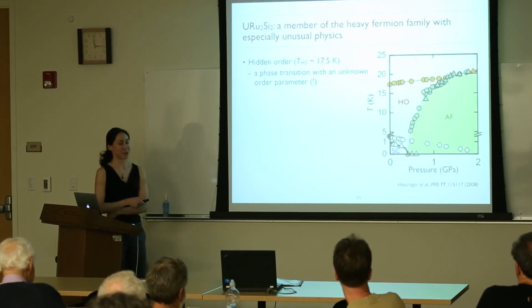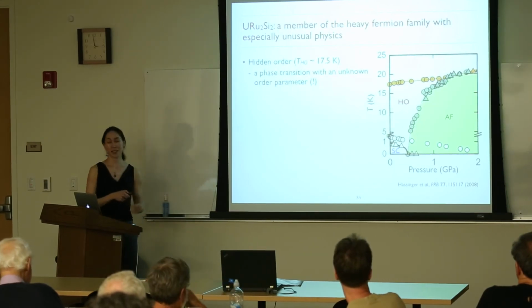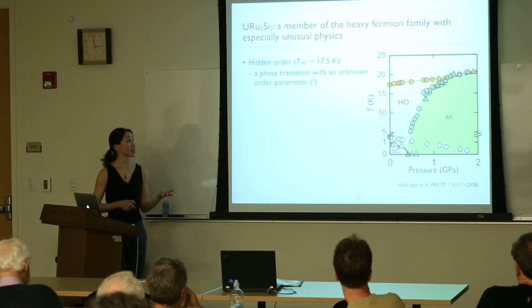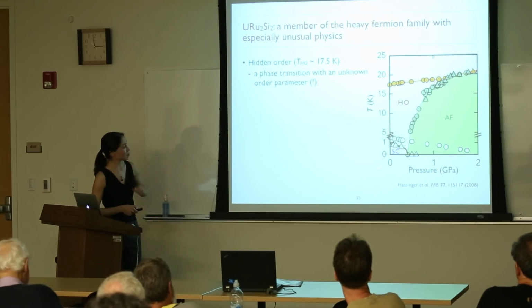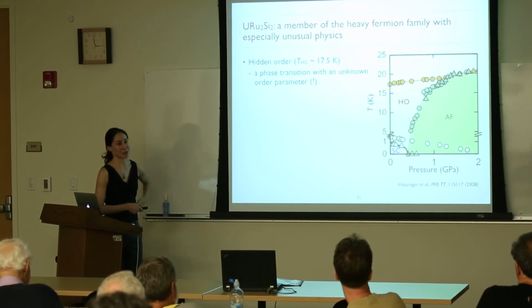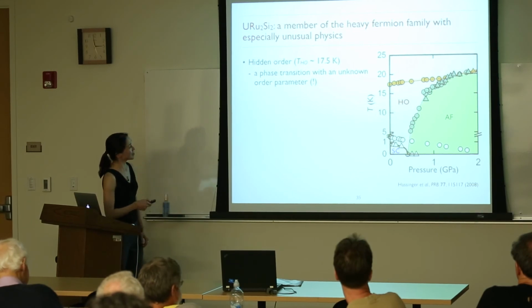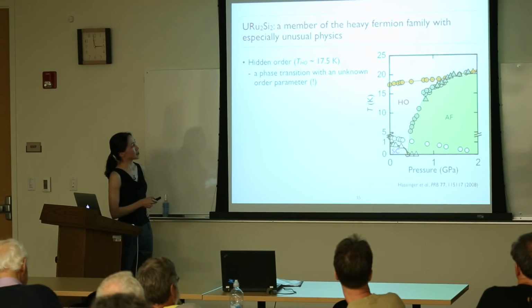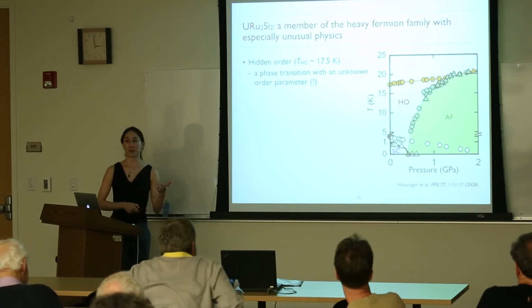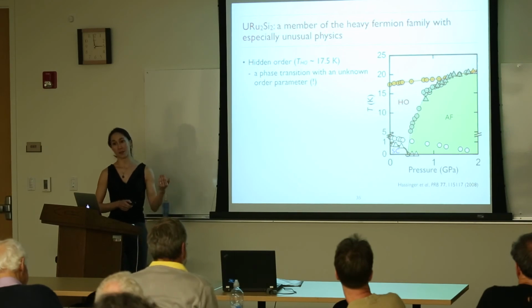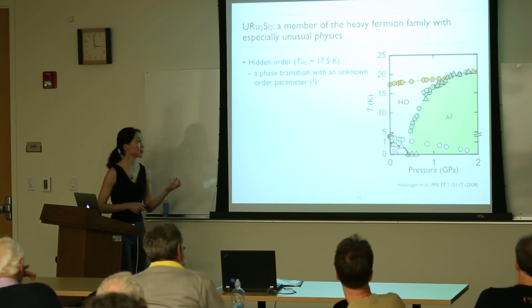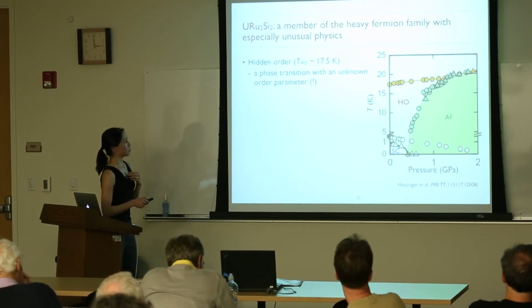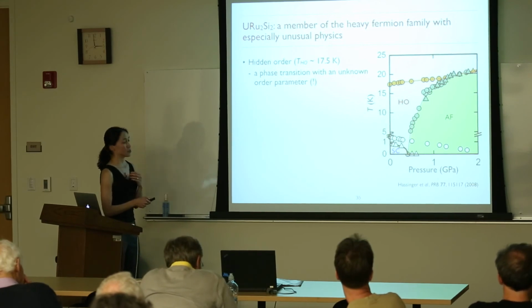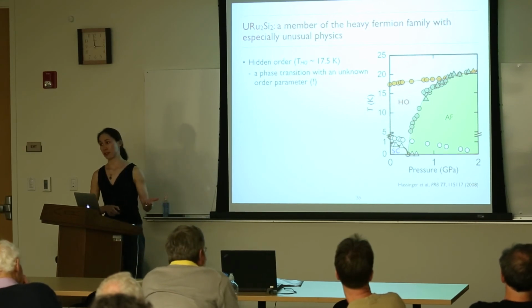But what's very interesting about URu2Si2, again, is that it has a very unique phase diagram. I've shown it here as a function of pressure and temperature. What's remarkable about it is that at about 17.5 Kelvin, you see a thermodynamic phase transition, so there's a discontinuity in specific heat. You can see it in resistivity as well. So you know that there's a phase transition here, and you should associate with that some sort of broken symmetry.